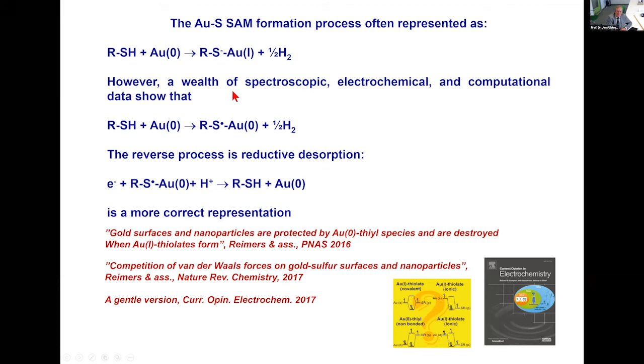The actual gold sulfur bond has commonly been represented as a gold 1-thiolate bond. But we know now, we like to believe, there's a wealth of spectroscopic and electrochemical and not least computational data to show it is not gold 1, it's actually gold 0. And so the sulfur, the thiol, is bonded as a thiol radical. This is the dominating process in gold sulfur bond formation. And the opposite process, as is written here, is exactly the reductive desorption.